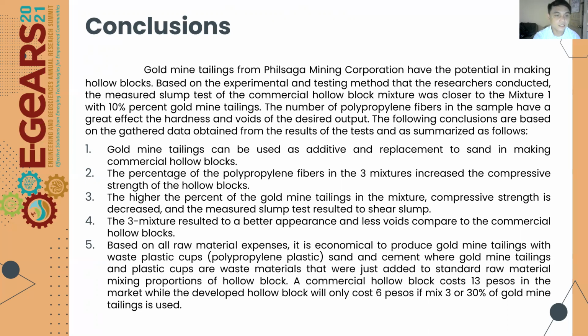Next, the three mixtures resulted in a better appearance and fewer voids compared to the commercial hollow blocks. Based on all the raw material expenses, it is economical to produce hollow blocks with gold mine tailings and waste plastic cups or polypropylene plastic. Sand and cement are standard materials, while gold mine tailings and plastic cups are waste materials that were just added to the standard raw materials mixing proportion of hollow blocks. A commercial hollow block costs 13 pesos in the market, while the developed hollow blocks will only cost 6 pesos if mix 3, or 30% gold mine tailings, is used.